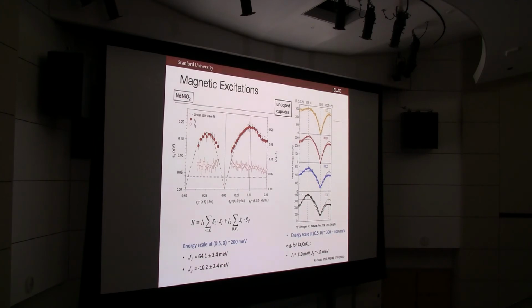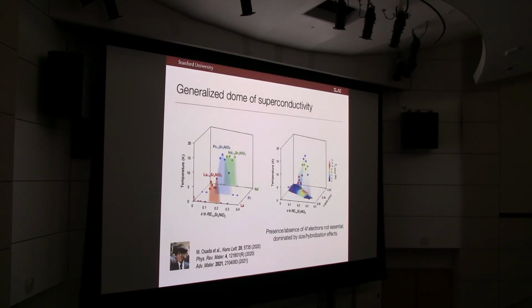A second feature observed in this experiment was that, whereas this is also Rick's data for the cuprates, those were resolution limited experiments, whereas in our case there's notable damping above our resolution limit by this dotted line. So this is something like the half width at half maximum of these peaks. And so clearly there's quite a bit of damping. It looks more like a doped cuprate, and we suspect qualitatively it might arise from this additional electronic channel.